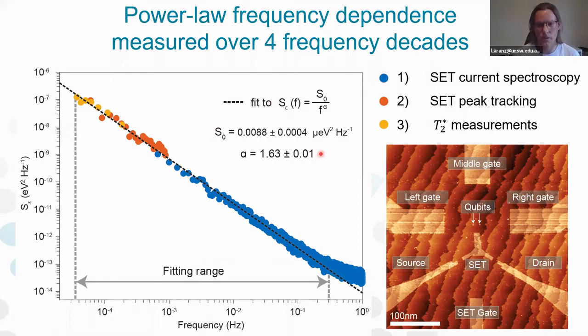So I just want to comment on these values that we measure. For alpha, we measure 1.63, which is not really pink, but not brown either. It's something in between. We need a new color to describe noise in this device. But what it tells us is that the noise is dominated by an ensemble of two-level fluctuators with a non-uniform distribution of activation energies. We can also conclude that some of these two-level fluctuators have really low switching frequency because we haven't even reached the limit of this power law spectrum.